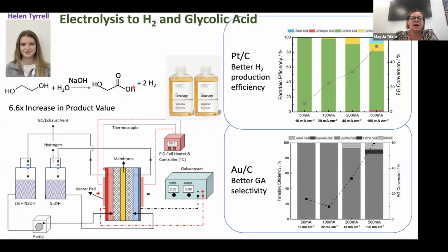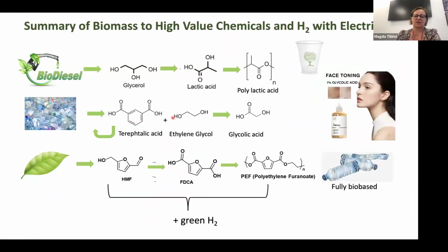And to do this electrolysis of ethylene glycol is much easier because you have 1 less carbon. So in fact, if you do it on platinum and gold, you still get glycolic acid with quite high selectivity. So I guess on platinum, you get better hydrogen. On gold, you get better glycolic acid. But you could do this at relatively high current densities, quite selectively towards this glycolic acid, which is nice.